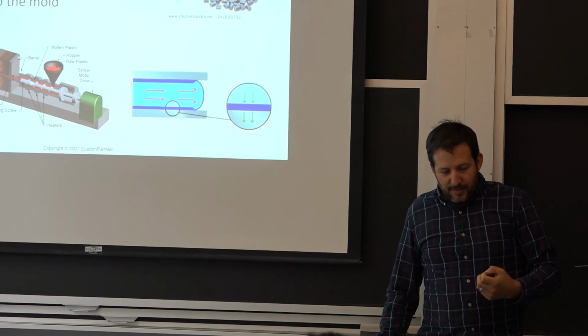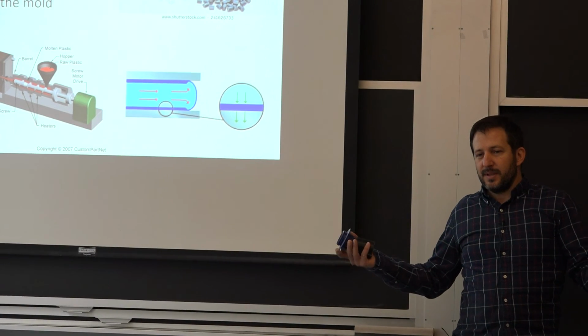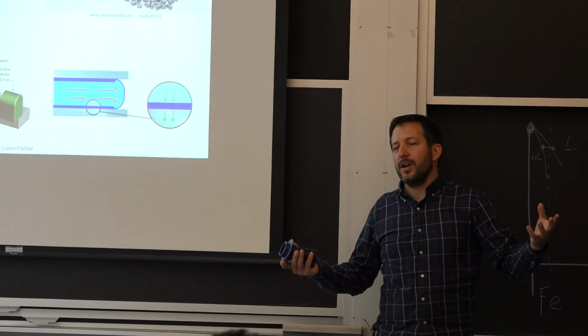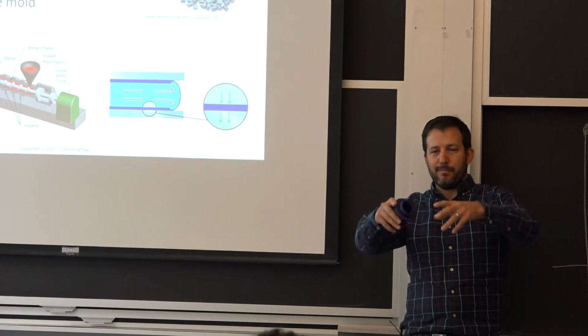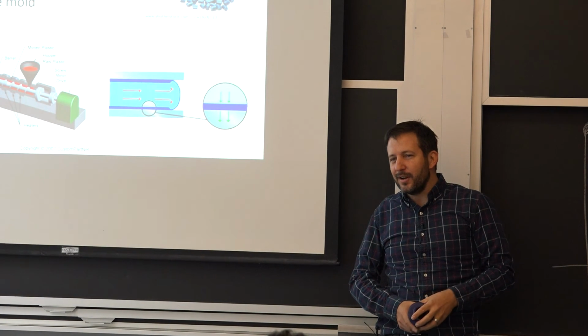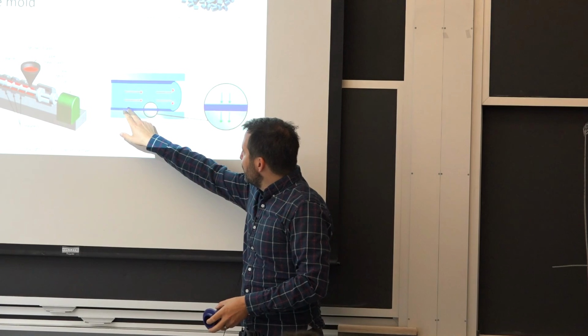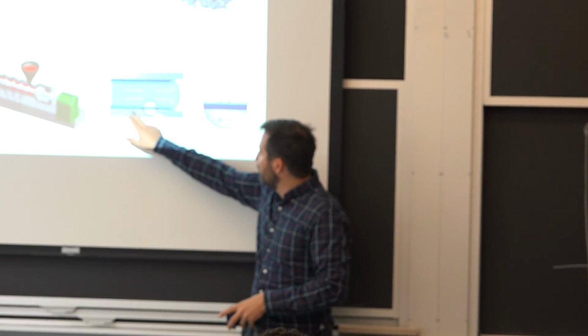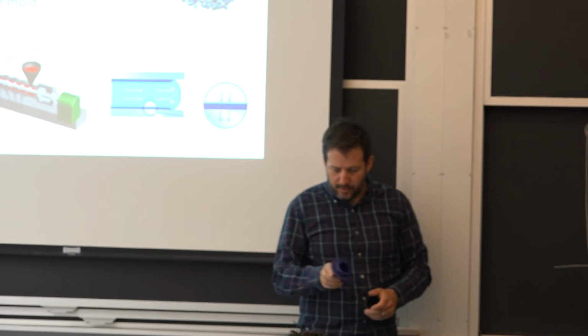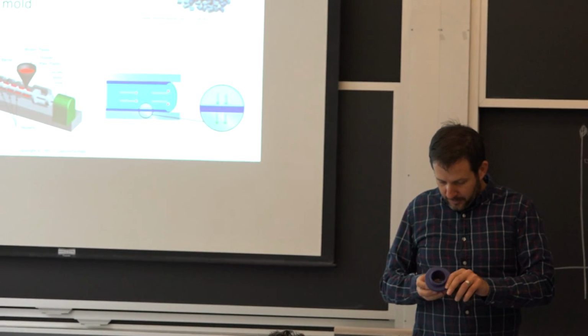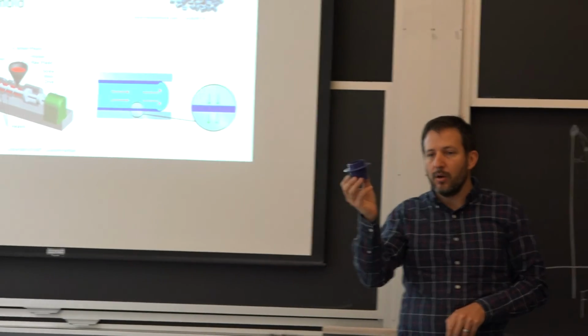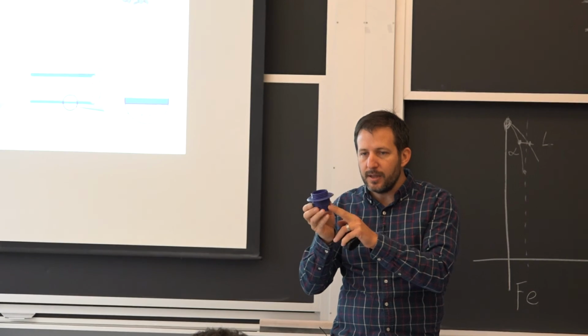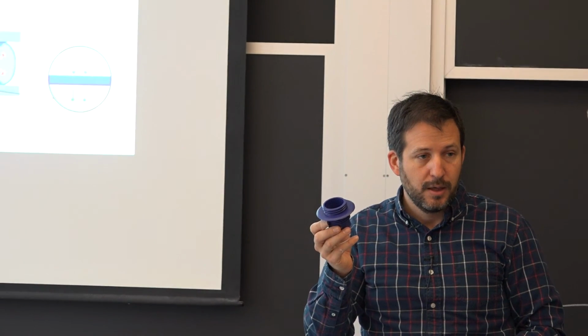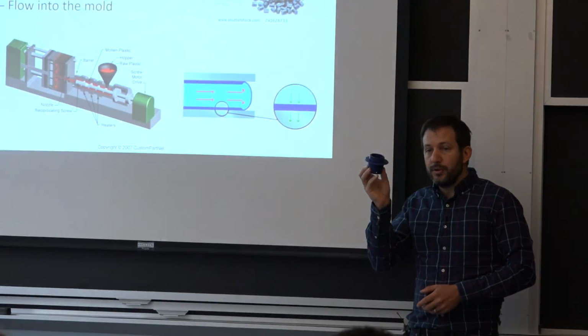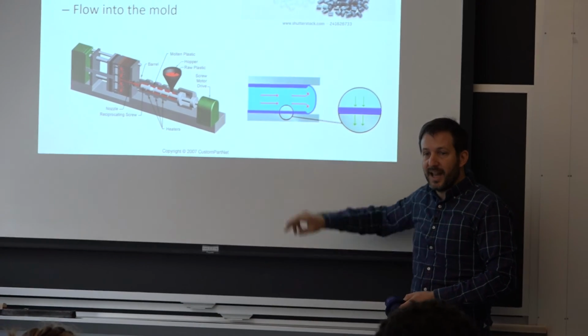It's not exactly like forming grains of crystals. You can probably think of this because everything is just so long that you cannot organize a macromolecule spaghetti into something that's very, very organized. It's just not going to happen. But what does happen is when you push it, you shear it, and you deform it, you form that skin. So if there's anything you want to bring home for your permanent knowledge base, it's that if I start grinding the surface and trying to polish it, it's not going to be as resistant to creep and fatigue and cracking as the original material. Most of the time, the as-molded geometry is more resistant because you form that skin.